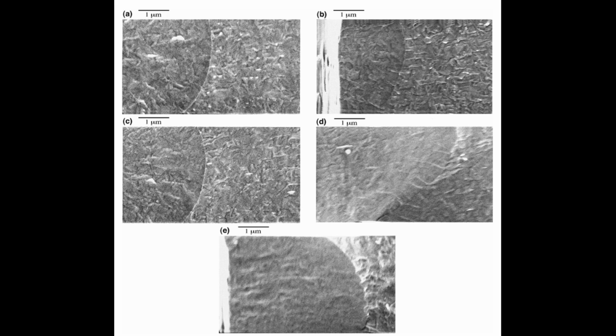But what about the variability? That's the key improvement. They note a significant reduction in the scatter of the data compared to the results from the indented and annealed samples. The plus or minus 0.2 suggests much tighter grouping. So less scatter, more consistency. Precisely. It suggests this newer, simpler method might be the way forward to get a more accurate and reliable value for the fundamental fracture toughness of polysilicon used in MEMS.